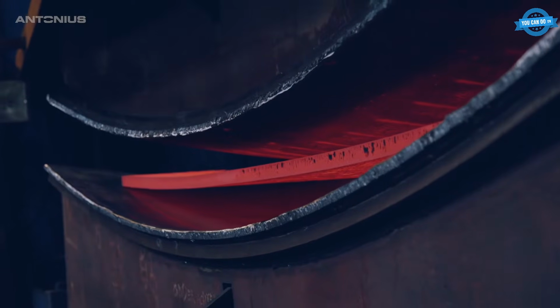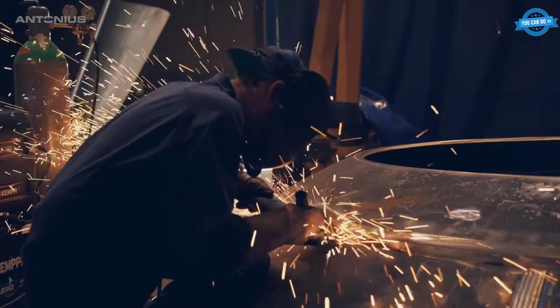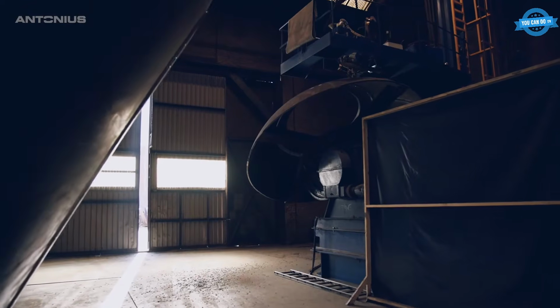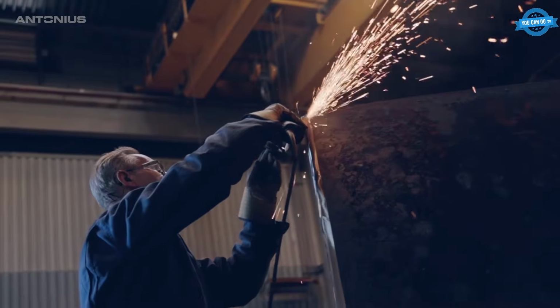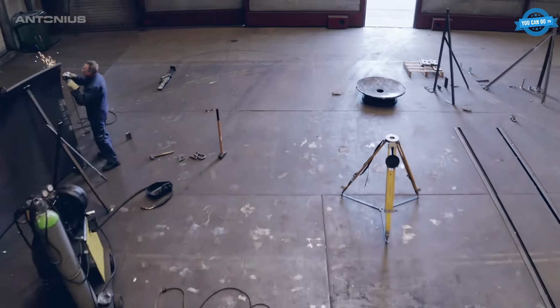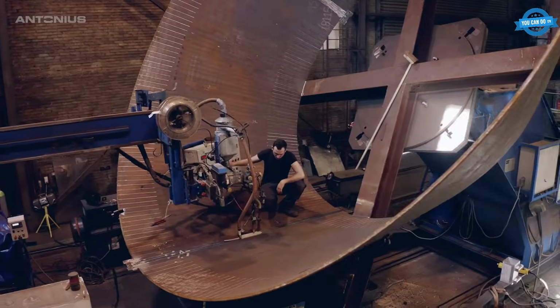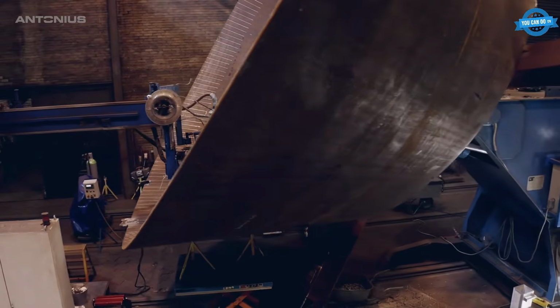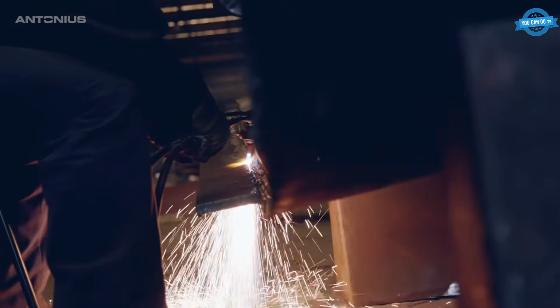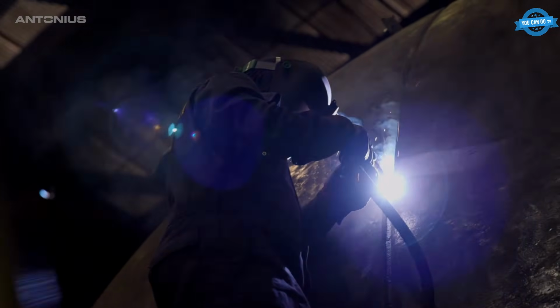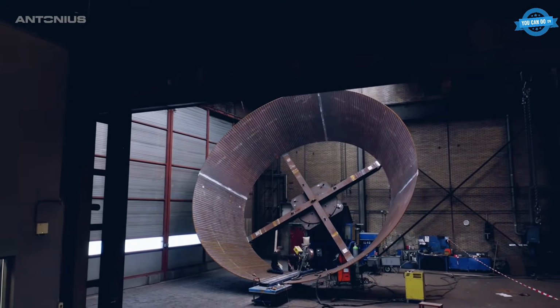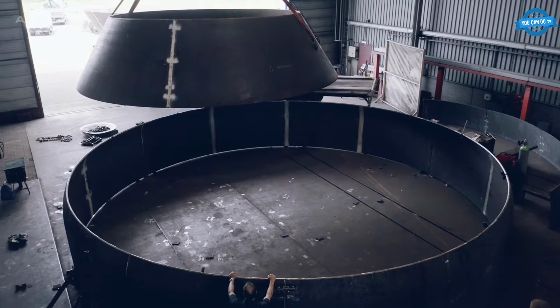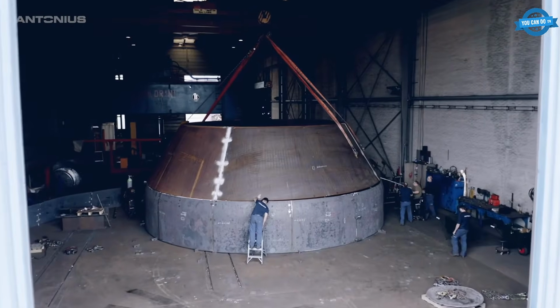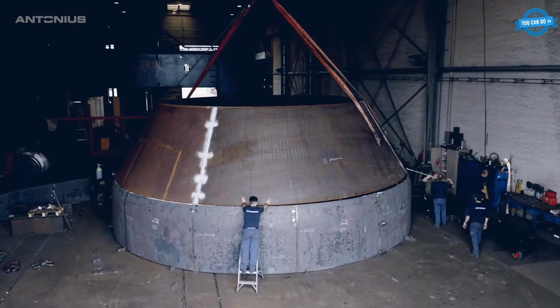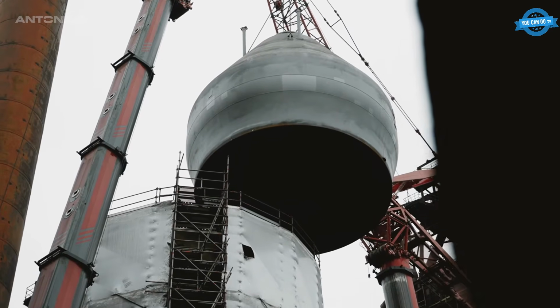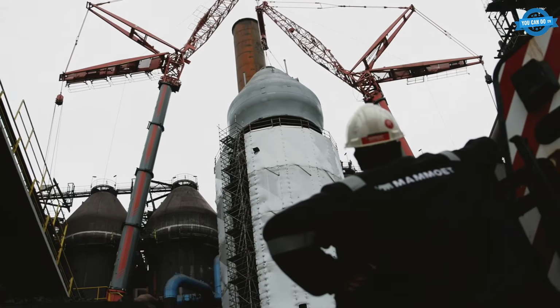And here's where everything from the previous scenes has to come together at once. A hot blast stove dome. The top section of a giant industrial vessel that heats air for blast furnaces at steel mills. Custom press molds get designed to shape the metal in one heat press with minimal rework. Multiple welding methods join the massive sub-assemblies. Test assemblies happen before final production. A 1% deviation over a 10-meter object leaves several centimeters of error. Far beyond acceptable tolerance. Over 10,000 man-hours went into a recent dome for European steel mills. Every millimeter counts when the finished piece is nearly the height of a 3-story building.